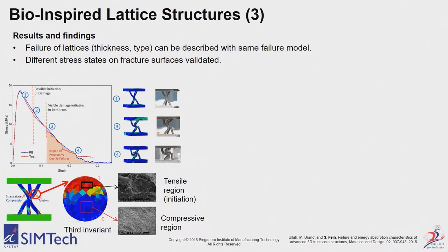The second issue was that the manufacturing process is not exactly the same dimension as actually designed. So when we print these very thin structures of about half a millimeter, they don't turn out exactly round. They come out a bit more elliptic, and that made a difference as well. So he spent a lot of time characterizing the real structure, but there's no data fudging in here. So this is the real dimension used, and proper strain measurements from the experiment lead to very good result with the numerical predictions. But what we can see now in the numerical analysis is quite a few steps that occur. So we have even way past buckling occurrence, we actually have damage initiating. We can numerically determine where that damage initiates. We can also see it on the high-speed camera.